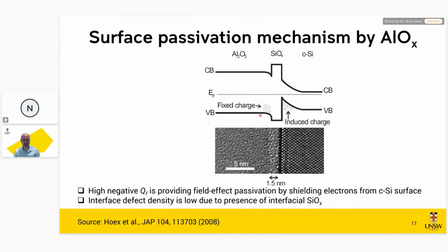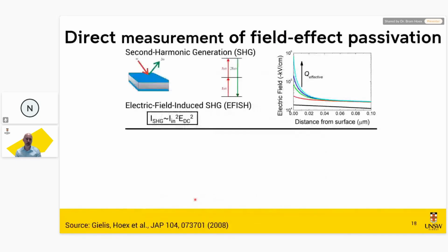This has a fixed negative charge that is present at the interface with the silicon oxide, which is unintentionally grown on crystalline silicon. So the negative fixed charge is here. And then your interface defect density is determined by the quality of your silicon oxide. So that determines your DIT. The fixed charge in your ALOX determines your field effect passivation. And both factors are affected in UVID.